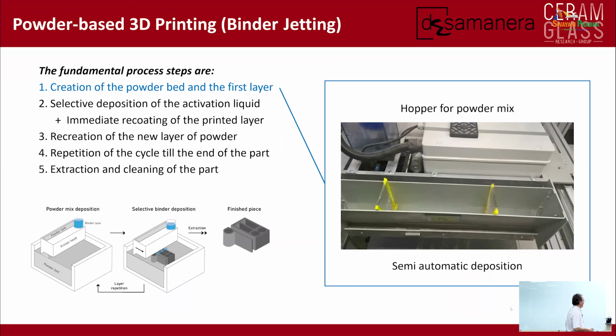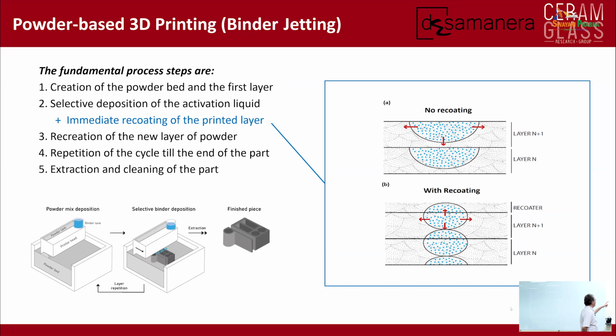So you have the creation of the powder bed and the first layer. So we put the powder here, and then there is a semi-automatic deposition of the powder. Then we have the selective deposition of the activating liquid. And what we do is that we deposit half the thickness of the layer.